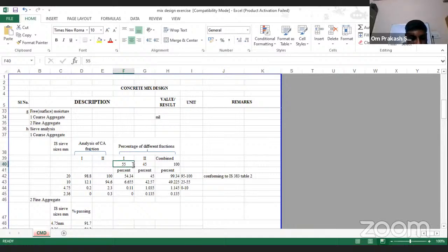If I make it 60, it is 45, 1 and 99. So you can see when I am changing the proportion of 20 mm and 10 mm, what is happening? Only the 10 mm sieve size is giving more variation, not the 20 mm sieve size, not 4.75, 2.36. So according to this, the value is 45, which is in the middle of 25 to 55. So this proportion is suitable for our concrete mix design.